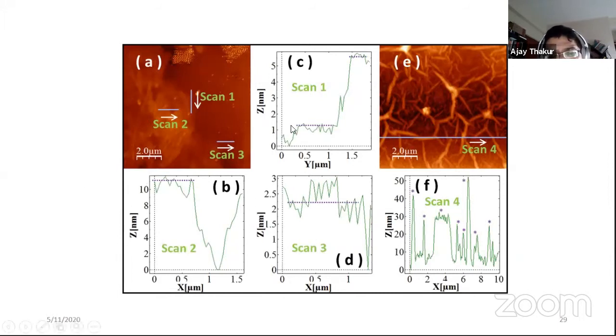A typical thickness of about 1.4 nanometer is the one which corresponds to the graphene oxide monolayer. Similarly, we could also see very thick layers as well. So all kinds of thicknesses were seen. It was also interesting to capture these wrinkles and their frequency. One can see that if you take a large enough sample area, then one can move across these wrinkles and see the occurrence of these wrinkled regions.